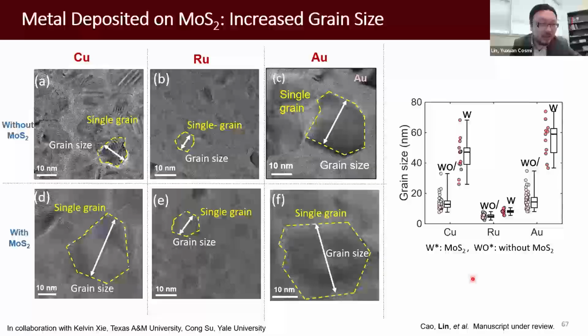Yeah, so I saw in the literature somebody has tried low temperature CVD or MOCVD, below 400 degrees Celsius, and they can grow a 2D layer on a trench structure conformally, and then we can do guided deposition of the metal. That's one possibility. Also, in our NSF FuSe team, we have Zhihong Chen from Purdue University. She worked together with a few companies. They developed this plasma enhanced approach. They start with a tantalum thin film. Tantalum is already used in interconnects, and they sulfurize it into tantalum sulfide at a low temperature using PECVD. That's also a very good diffusion barrier. She only focused on the diffusion barrier at that time. Right now, we're also exploring if tantalum sulfide also works for the templating effect.